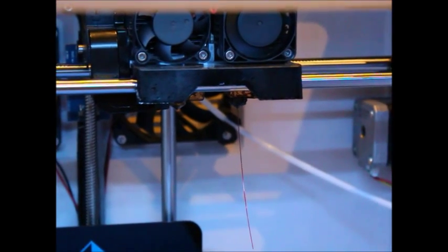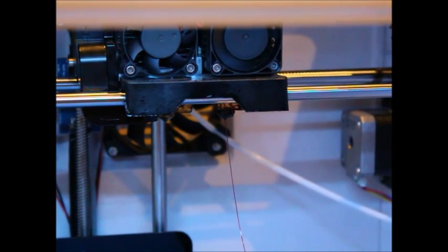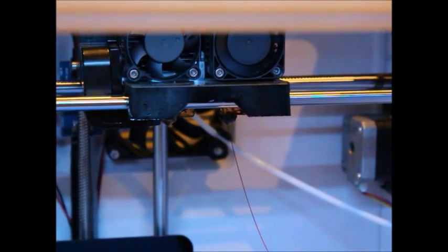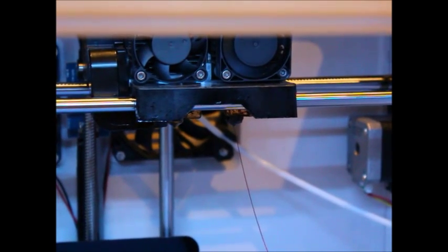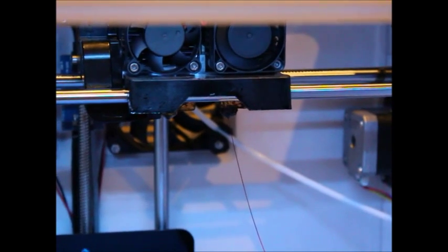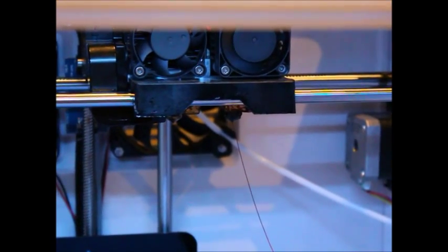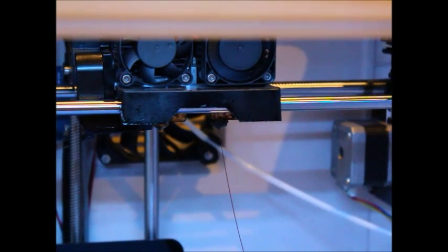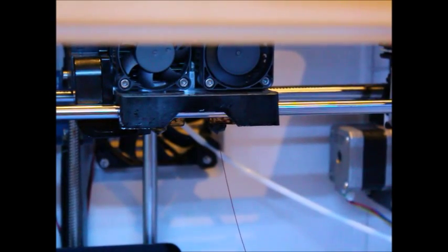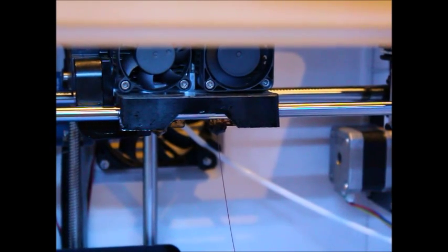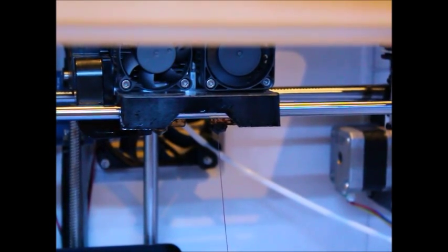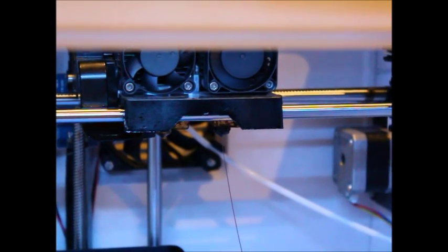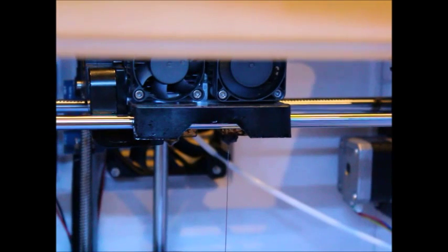Just keep in mind when you are setting up your print that you are printing at really low speed. Probably the recommended speed is about 10 to 30 millimeters per second. If you go any faster than that, what will happen is that the filament will wrap around the gear and it will jam. So it is not recommended. The temperature is anywhere between 175 and 200 degrees. It is recommended. You can try on your printer, it might be slightly different, but it will be somewhere in that range.